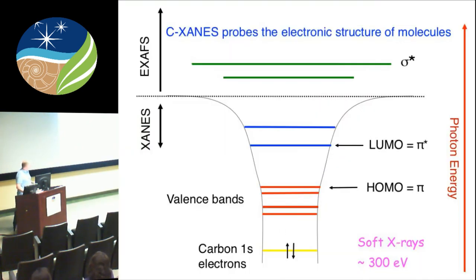The core of the spectroscopy is very simple. It's that the 1s electrons are not involved in any bonding whatsoever. They don't even know they're in a bond, basically. They're interacting very strongly with the nucleus. However, if you excite these resonantly with soft X-rays, at the critical ionization energy, you can promote one of these electrons into the antibonding orbitals, which are unoccupied. In the antibonding orbitals, basically now that electron knows it's in a bond, and it will report that as an absorption feature, and I'll show you how that works.